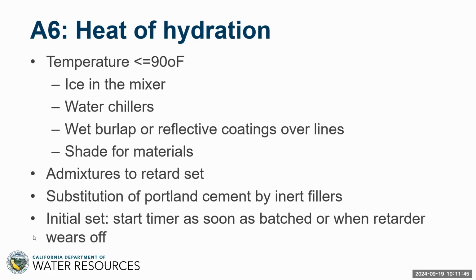And just as a practical point for folks in the field, initial set, start your timer as soon as the grout is batched. That's time 0. But if you're using a retarded mix, start time 0 for initial set when the retarder has worn off. And you should know that because you're going to see a marked rapid increase in the marsh value. Okay, so heat of hydration, very important, especially in a state like California with very high ambient temperatures in many areas. Okay, James?